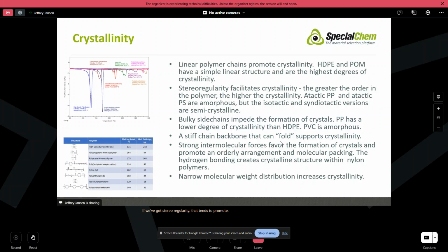So things like atactic polypropylene, atactic polystyrene, they're amorphous, but the isotactic and syndiotactic versions, because they're more stereoregular, they're semi-crystalline. Bulky side chains, like we saw in the previous example with the polyphthalate, again, they tend to impede the formation of crystals. Polyvinyl chloride, PVC, has that big chlorine atom sticking off of that. Again, impedes any crystalline structure.